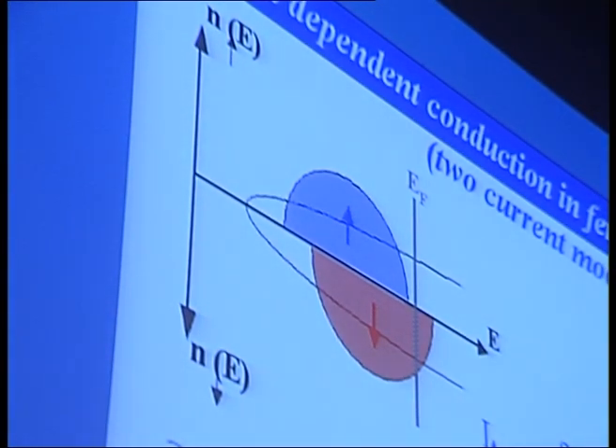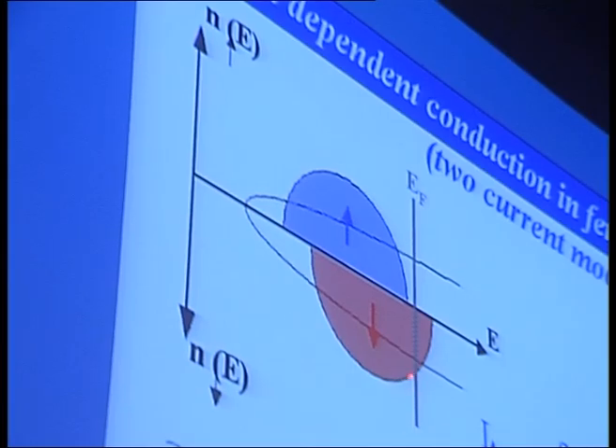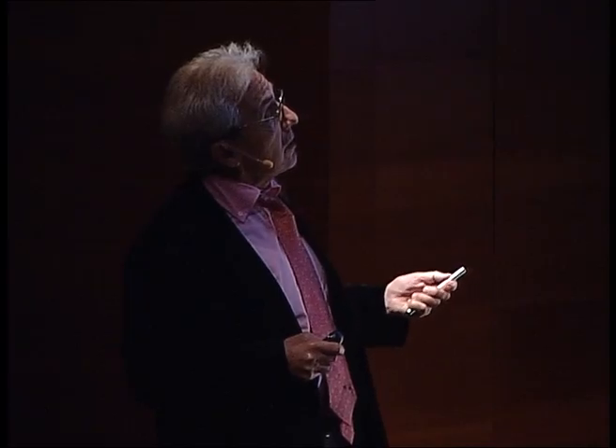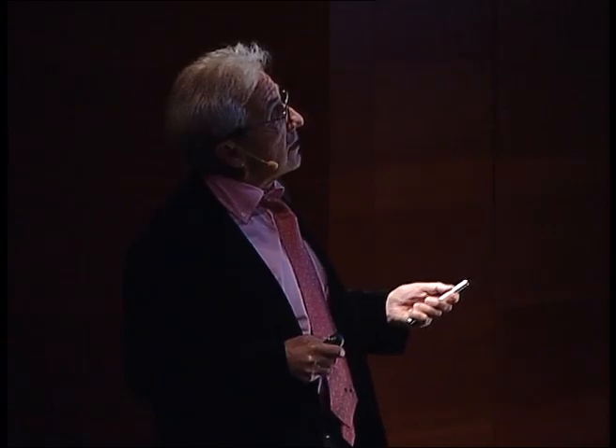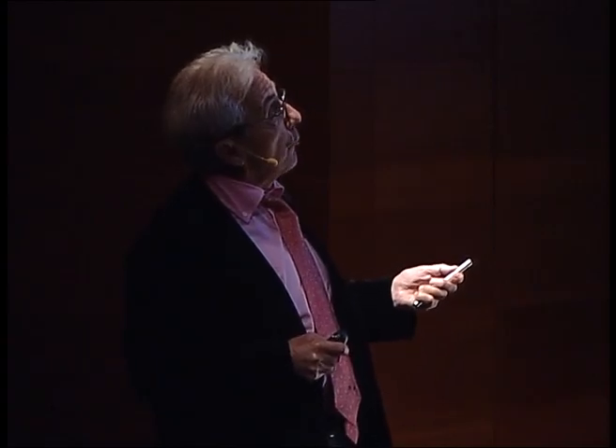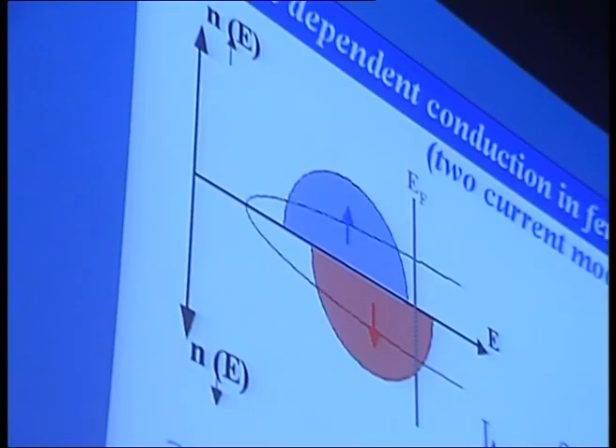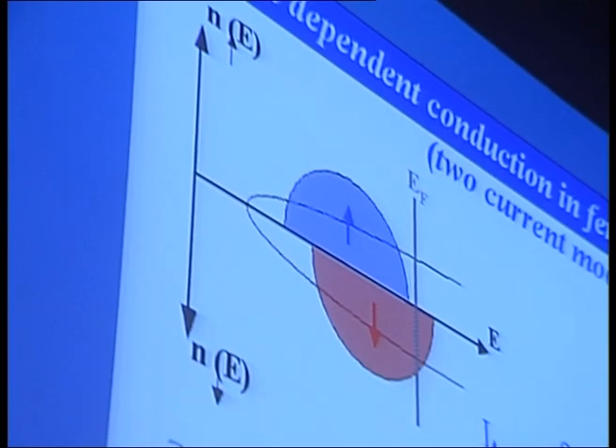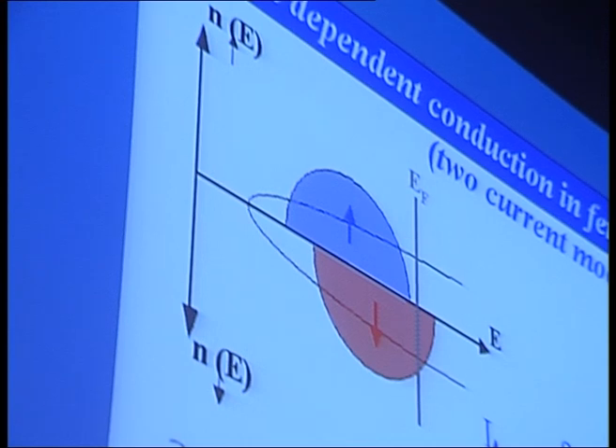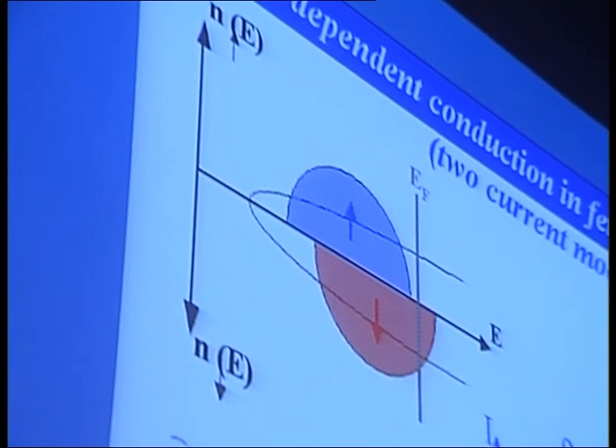And if one considers the electrical conduction, which is controlled by the wave function of the electron at the Fermi level, one sees that the wave functions are completely different. The electron states are different at the Fermi level for the two spin directions, and very generally there is a spin-dependent conduction. And in first approximation, it can be described by a conduction by two channels in parallel, spin up,